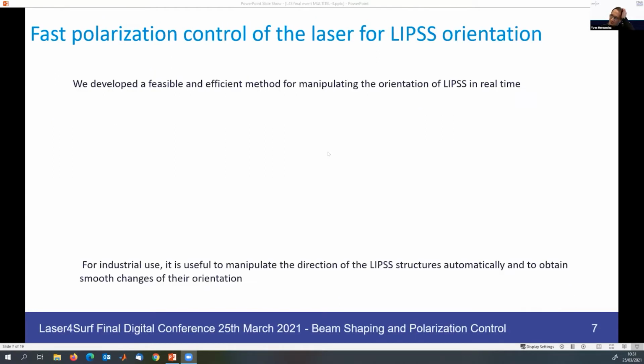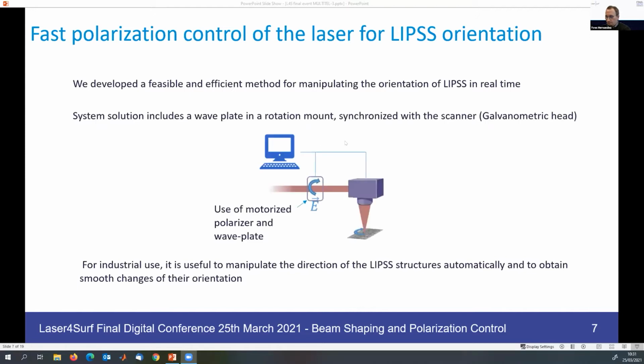So we need something that is quite easy to use, that can work in real time, so it can be very fast, and that can be interfaced with the scanner. We use quite an obvious solution, which is to use a motorized polarizer and a wave plate. So this system was implemented rapidly at the beginning of the project and interfaced with Lasea system. It permitted to control the orientation of the polarization rapidly, well, almost in real time.